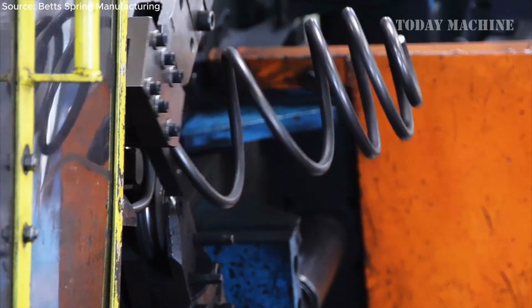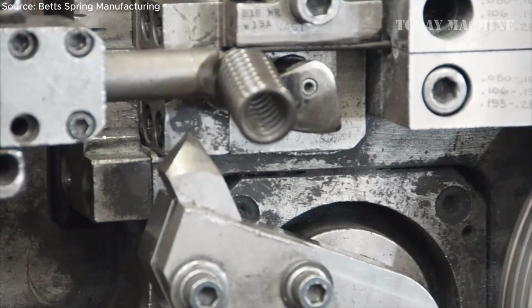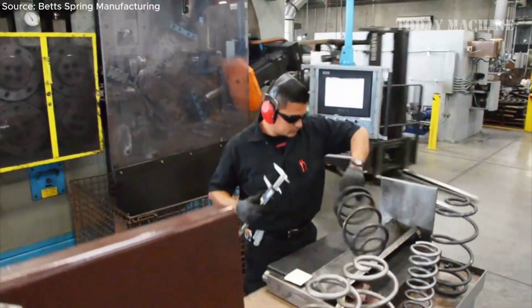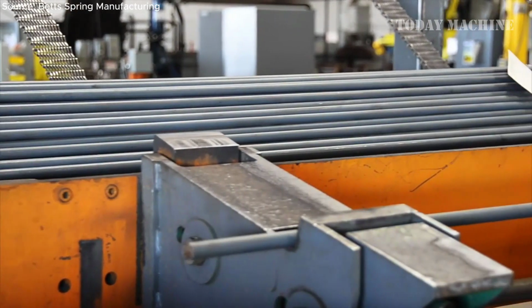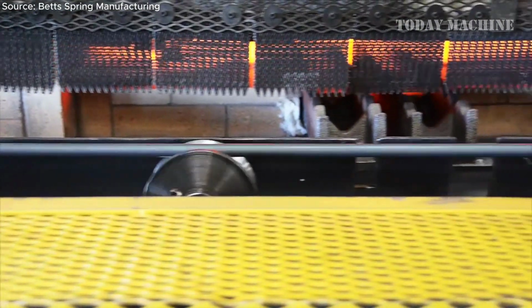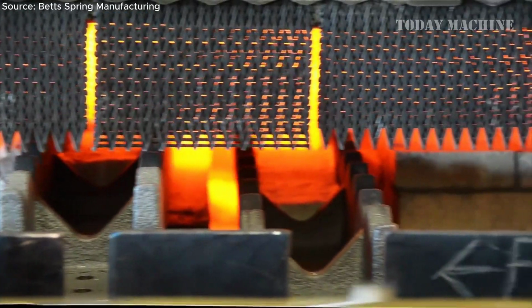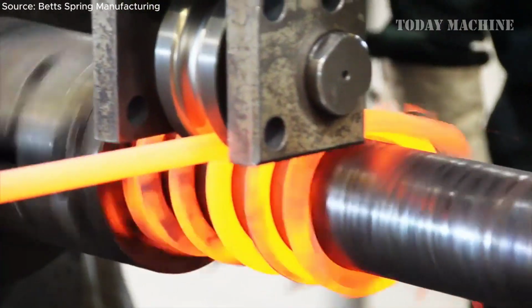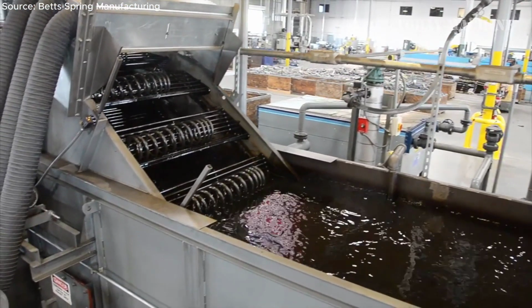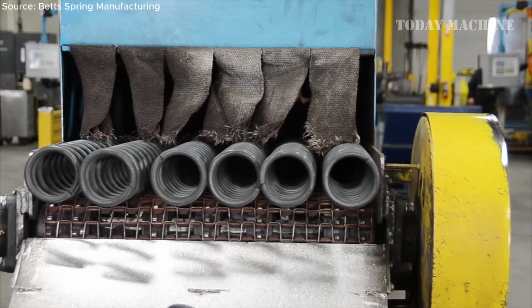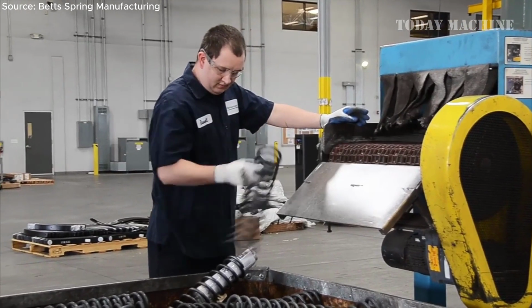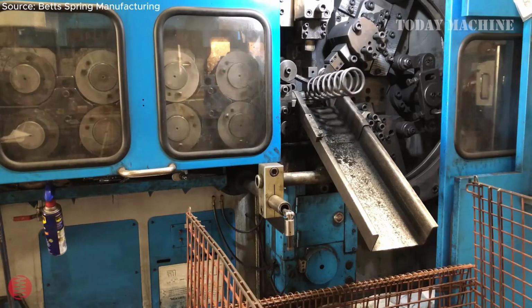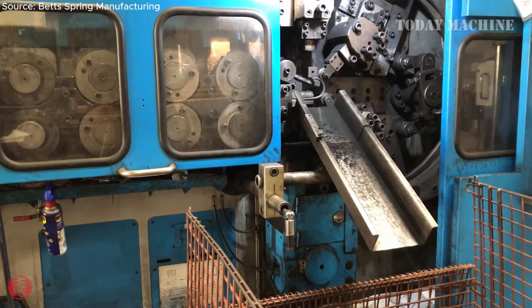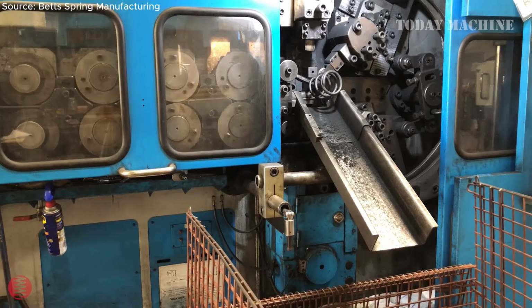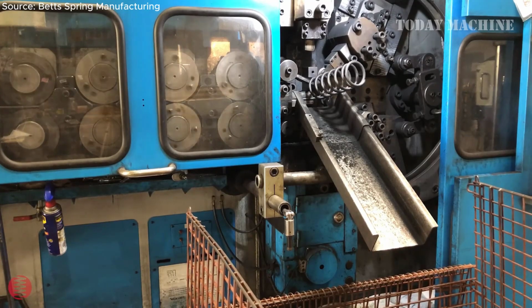Cold winding and hot winding are two distinct spring manufacturing processes. Cold winding uses high-tensile chrome silicon for lightweight, high-deflection springs, while hot winding forms larger springs by heating bars to 1,750 degrees Fahrenheit before coiling, quenching, and tempering. In cold coiling, wire moves through rollers and fulcrum pins, wrapping around a fixed mandrel to form coils.